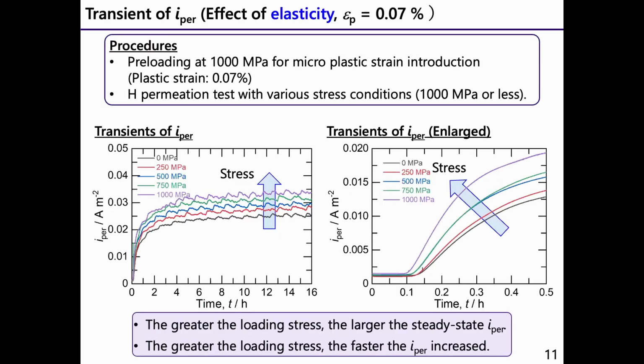In order to investigate the effect of elasticity on hydrogen diffusion behavior, we first introduced microplastic strain by applying preloading at 1000 megapascal. The introduced plastic strain was 0.07%. Then hydrogen permeation tests were conducted with various stress conditions, 1000 megapascal or less, to keep the microplastic strain constant. The left graph shows the transient of the hydrogen permeation current. The greater the loading stress, the larger the steady-state hydrogen permeation current. The right graph shows the enlarged graph in the initial half hour. The greater the loading stress, the faster the hydrogen permeation increase.